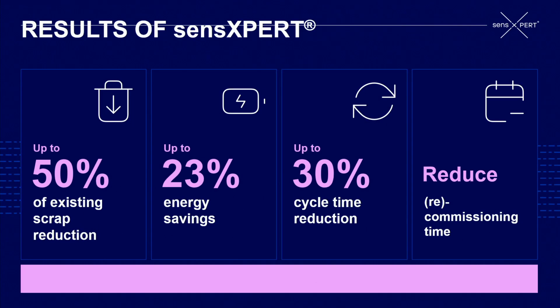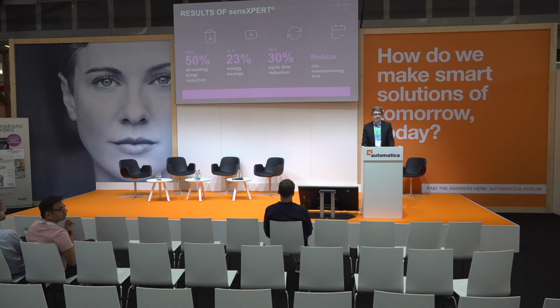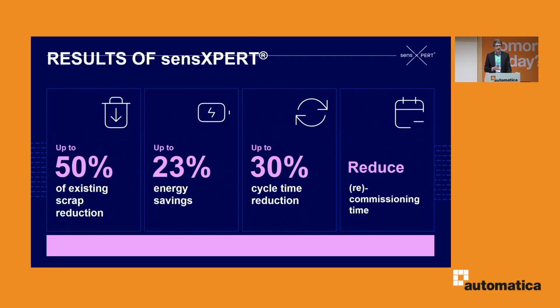And in the end, these are basically the ideal predictions, but what we have realized up to now is scrap reduction and cycle time reduction in significant quantities. And also, these lead, of course, to ecological improvements of the entire process. And there are also side effects, such as reducing machine downtimes due to looking for a problem that we cannot really identify. That's where this increased transparency of the entire process is really helpful. And of course, we have documented quality, right? We have a way to measure and document that quality criteria have been met here.